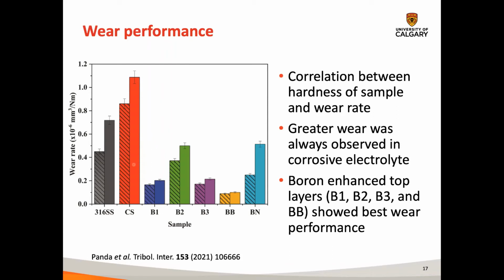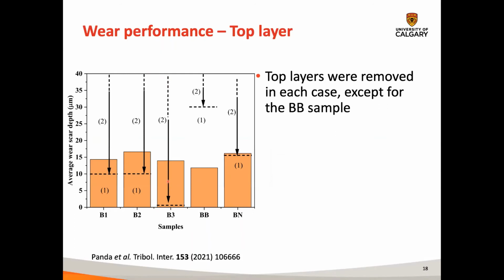Right, so again, when we compare the wear rates here, the boron enhanced top layer performs the best of all the different samples, in both dry sliding and in the electrolyte. And the carbon steel performed the worst, which is sort of obvious from what we know about carbon steel. And in general, all boronized top layers did pretty well, with low wear rates.